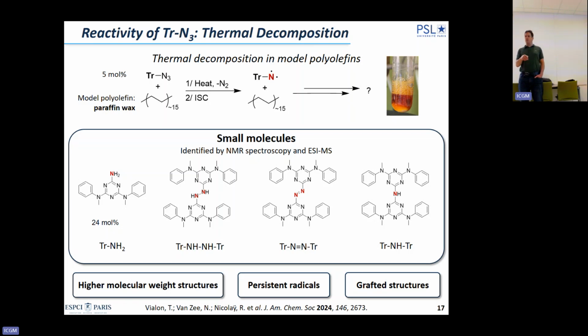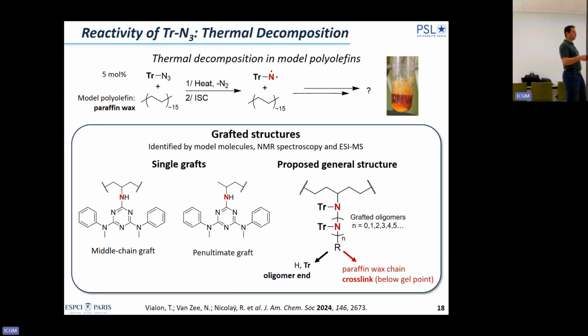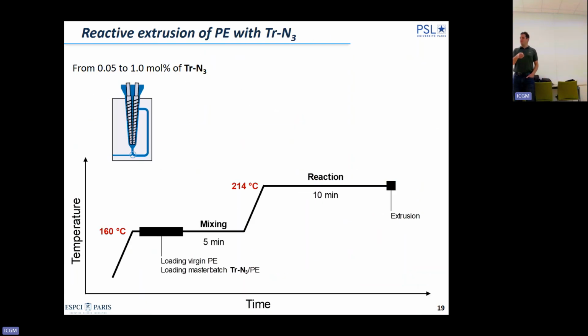The amount of these small molecules formed really depends on the condition and the amount of additive added. But we also saw in bulk or even in paraffin wax that we are making high molecular weight structures. Persistent radicals that were identified by EPR, and grafted structures. And if you look at the grafted structures, we really spent a lot of time analyzing them by NMR, ESI-MS, MALDI-TOF. We saw monografts at the end, in the middle, and we saw also oligomeric grafts with nitrogen bonds, okay? Polyazine type of structure. If you want more details, read this very nice article.